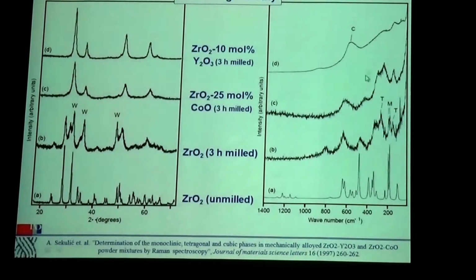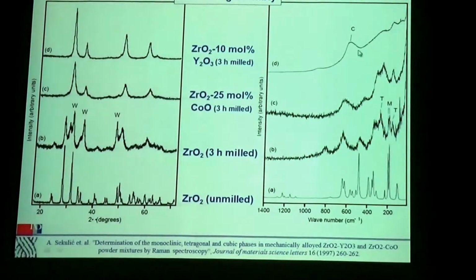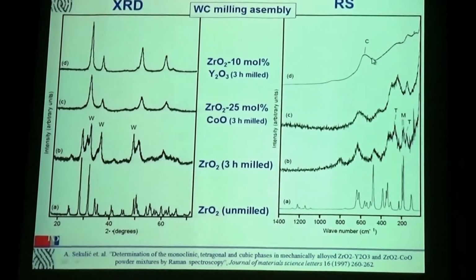So using Raman spectroscopy, we can easily recognize the difference between cubic and tetragonal structure. It is easily understandable, because if you have a cubic system and vibration, it will vibrate symmetrically, just in one way. If you have something stretched, you will have much more possibility of vibration, many more modes. So for tetragonal structure you will have 6 modes, for cubic you will observe just 1 mode.